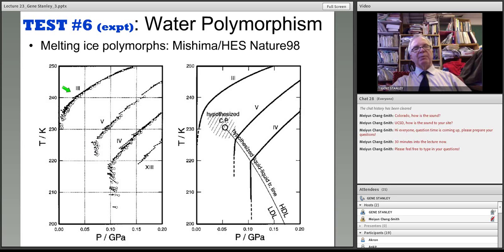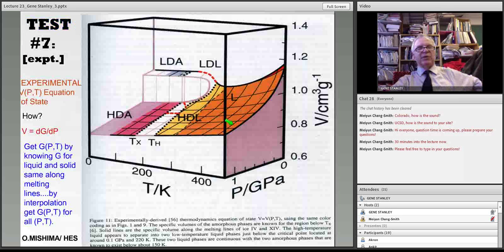At very warm temperatures up here, there's no kink at all. So from these data, we infer this phase diagram. Here is the line of hypothesized liquid-liquid transitions separating LDL and HDL. Here are the two lines I just showed you with kinks, and here's the third line with no kink. And that locates not exactly where the critical point is, but a range of temperatures and pressures between this line and that line, but it's fairly striking evidence that bulk water has properties that are consistent with the hypothesized liquid-liquid transition. You get something else out of this.